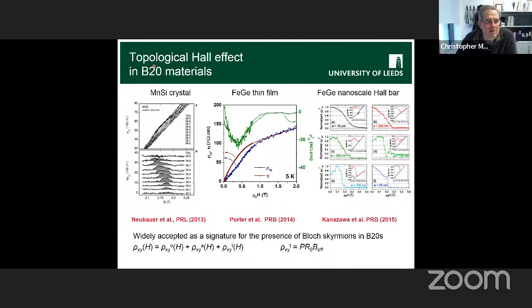And it was first found in the same materials that Skyrmions were first found in, these B20 materials. So this is a single crystal of manganese silicon, and there's a certain range of fields where it has a Skyrmion phase. And in that phase, we can see this sort of excursion in the Hall resistivity. This was a thin film of iron germanium that we made. And again, in the Skyrmion phase, we get this sort of excursion in Hall signal. And this was the Tokura group in RIKEN. They made a little nanoscale Hall bar out of iron germanium. And they see these traces with jumps and steps in. And they identified those as being the motion of individual Skyrmions moving around within the little Hall cross that they were measuring.